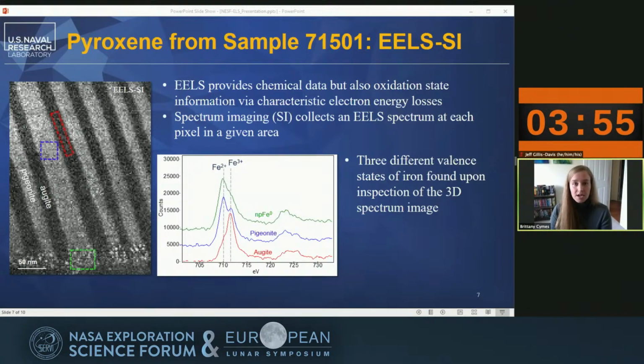Taking a look at a slice of this data corresponding to the characteristic iron excitation edges, we noticed dramatic shifts in the shape and onset of the iron L edge, which correspond to different oxidation states of iron. We found Fe2+ in the pigeonite lamellae, Fe3+ in the augite lamellae, and metallic iron in the nanophase iron particles.